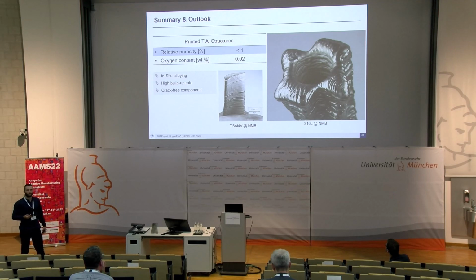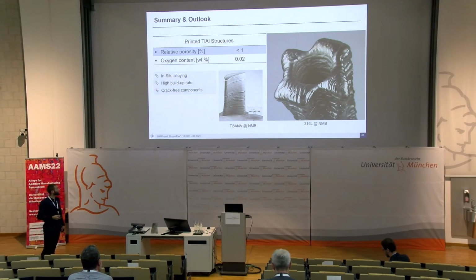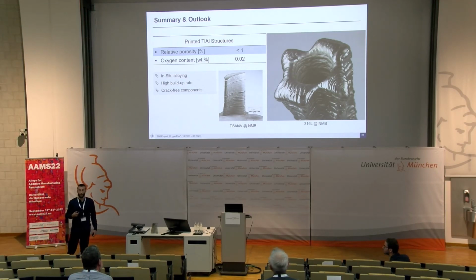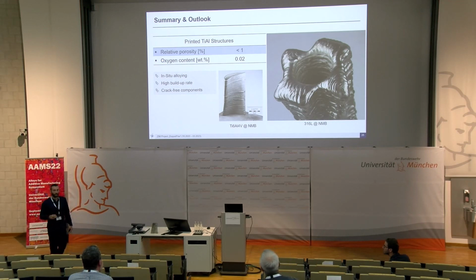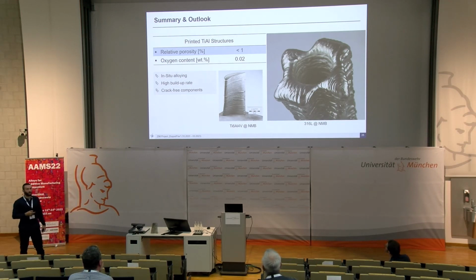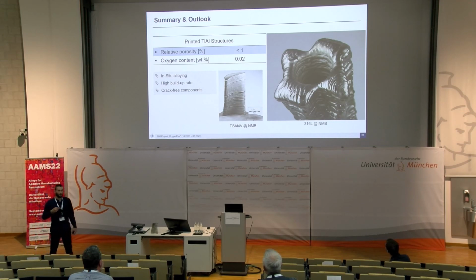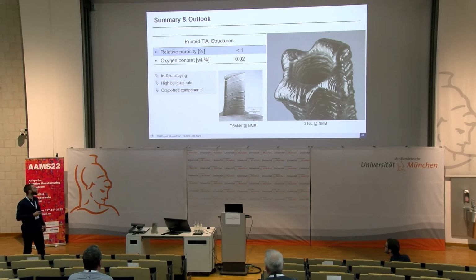To give you a summary and outlook of what we did, and maybe two interesting values. The parts we printed have a porosity of less than 1%, so it's basically completely dense. And we have an oxygen content of 0.02 weight percent. Compared to normal titanium powder, which has 3 to 5 times more oxygen in it when unprocessed, the oxygen content is pretty low.